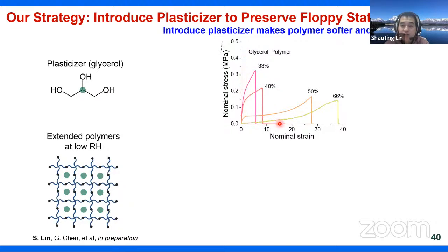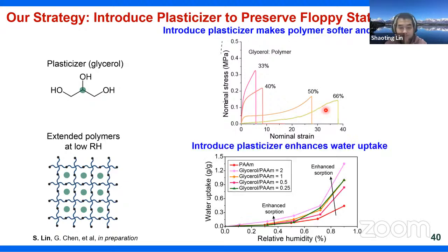And here we further perform mechanical calculations. We can see that as we increase the amount of glycerol, the material becomes softer and more stretchable. This gives us the confidence that the presence of glycerol is able to suppress the crystal domains and preserve the floppy amorphous polymer chains. And we further show that as we increase the fraction of glycerol, the sorption capacity or water uptake indeed increases accordingly.